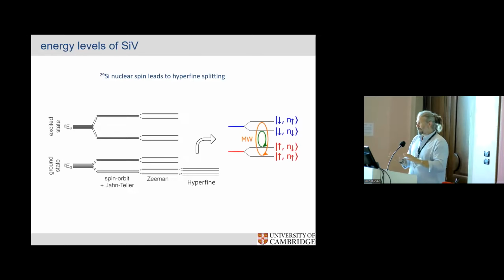And in the end, if you do it well, you can use the techniques developed previously, but employed by the nitrogen vacancy center, the optically detected magnetic resonance, to actually address these electrons, the final ground state being electron spin up or down, and the nuclear spin associated with it being up or down. You see how I'm building up now the story of the processing qubit plus the ancilla nearby. There's a nearby nuclear spin that's coupled, and that becomes your two systems. As long as you have the optical transitions, that's your trio that we talked about.